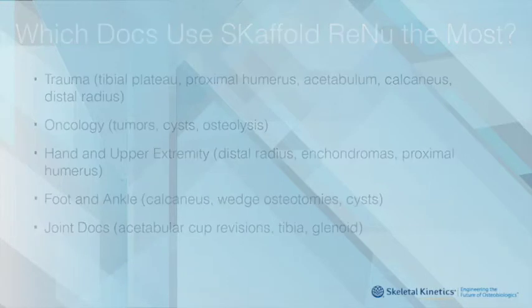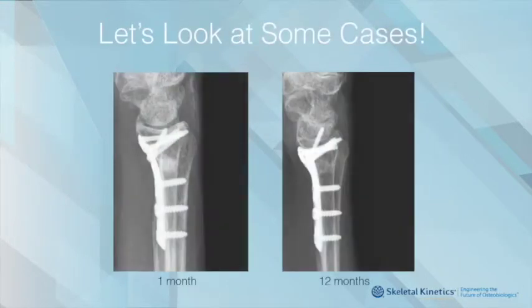Now let's look at the type of cases where Renu is used. In these two images, we see that Renu was used to fill a void associated with a distal radius fracture. The image on the left shows Renu just after 1 month. You can see the radiopaque area, which is Renu, and it has filled the distal radius void. The image at the right is a 12-month post-op X-ray. Here we see the vascular macroporous nature of Renu has resulted in fast bone remodeling. As we see in this image, nearly 75% of Renu has been replaced by host bone. These results prove that Renu is a unique graft, one that combines both strength and fast remodeling properties.